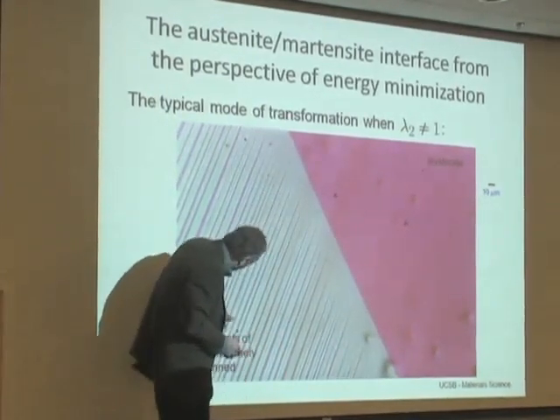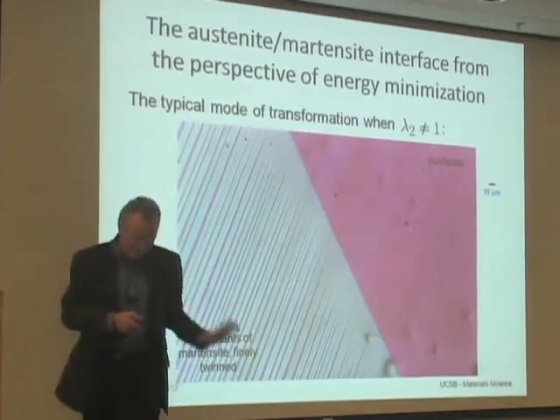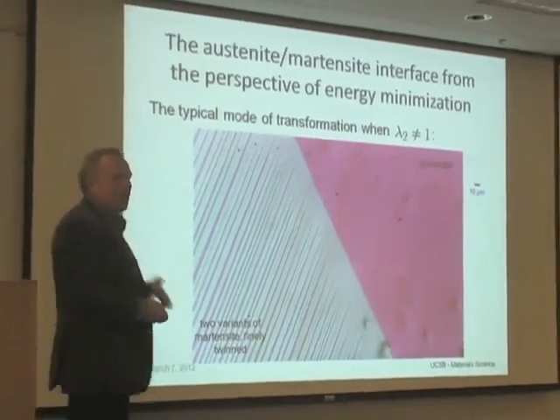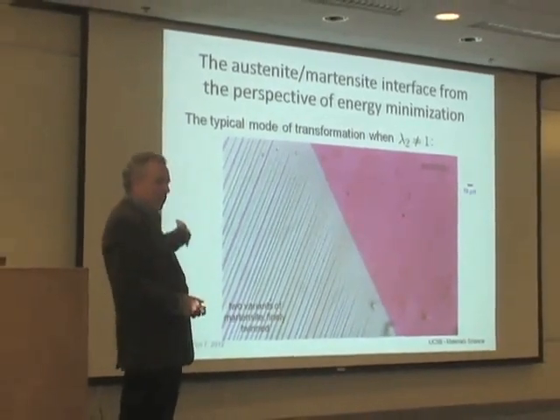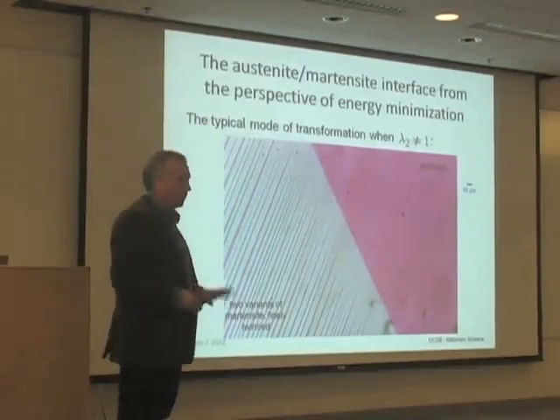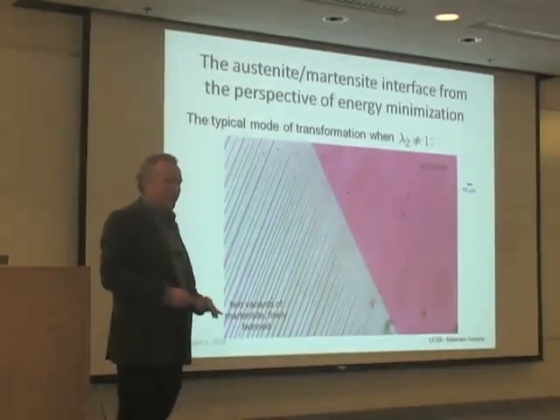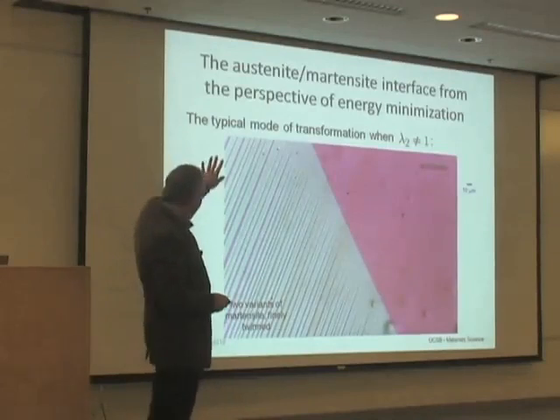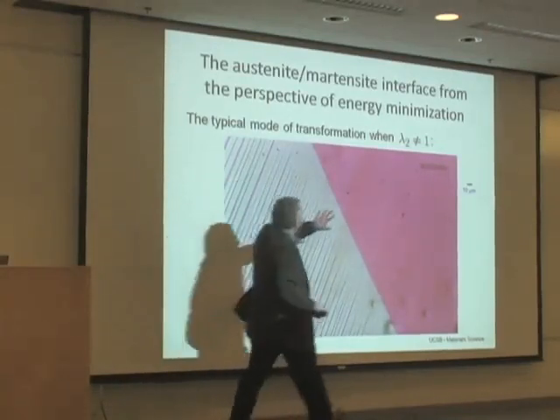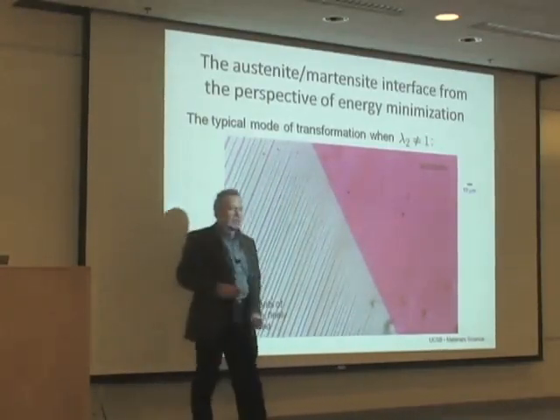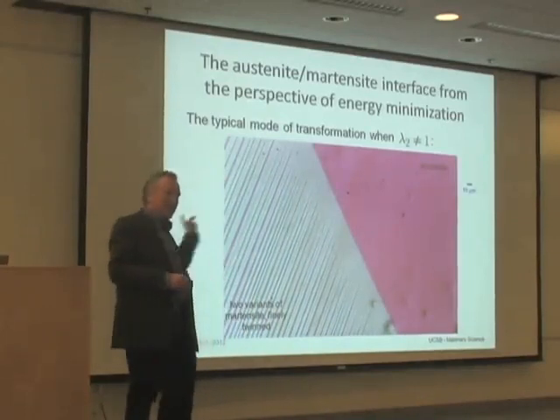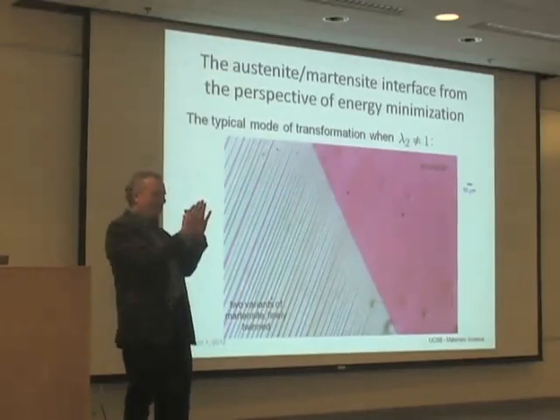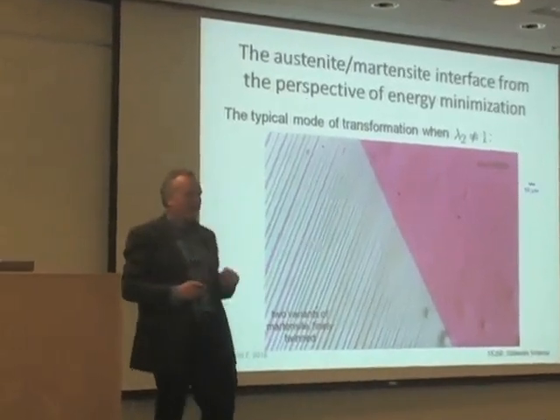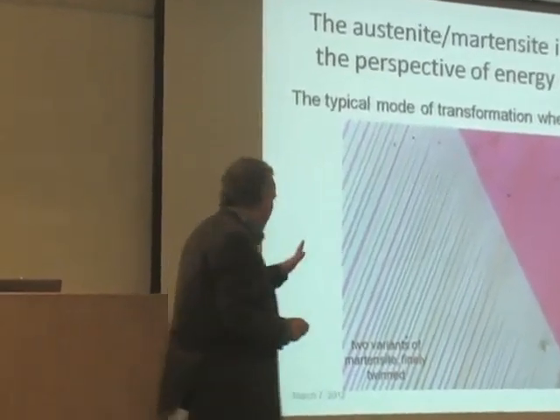This is what you see when you don't bother to tune. This is your typical martensitic alloy. If you tune to lambda 2 equals 1, what you see is austenite and a single variant of martensite over here. And the reason that needle was there was because lambda 2 was not quite 1. That's the point. But this branching is thought to occur to enable a further reduction of the elastic transition layer energy here without too much penalty of interfacial energy. That's thought to be the reason.